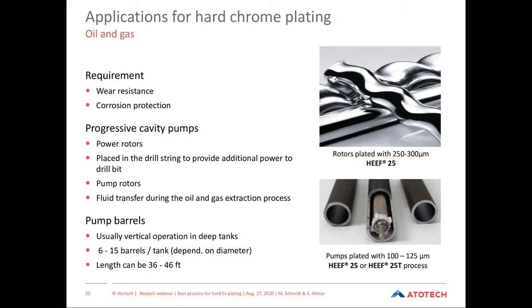These parts usually get very, very high thickness of 250 to 300 micron because they have to withstand very strong, partly very strong chloride or sulfur dioxide atmospheres, which are attacking the chrome very, very strongly. Another part in this field are pump barrels. This is actually the barrels which transport the oil or gas out of the ground. They are inside plated typically in very, very deep tanks. And since the parts are very long, up to 46 feet, usually there is a shorter anode used, which is traveling inside the barrel during plating up and down in order to provide the current which is needed for the plating.